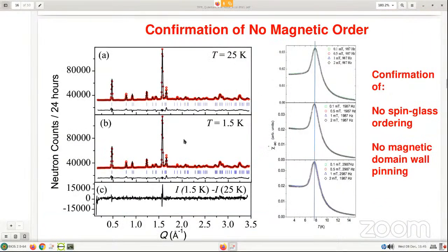Now we have also done the neutron diffraction experiment to confirm that indeed there is no magnetic ordering, and you see the difference pattern of the neutron diffraction intensity, the 1.5 and 25 Kelvin difference pattern, which tells you it is perfectly flat. So that means there is no magnetic ordering at all. That is very much confirmed.